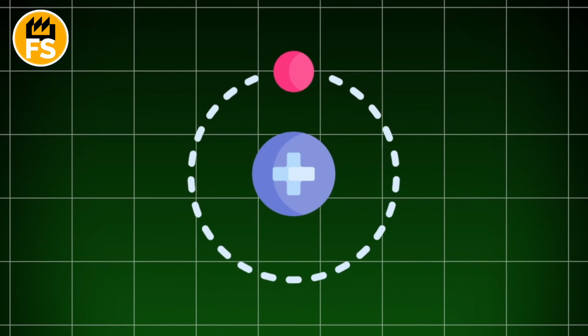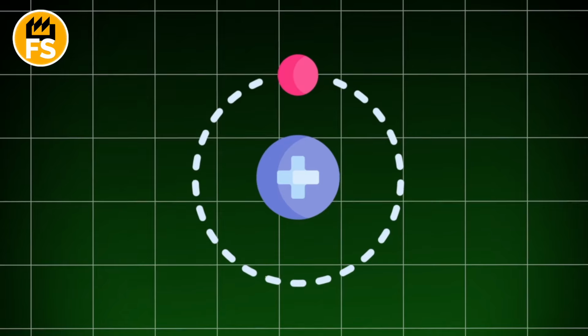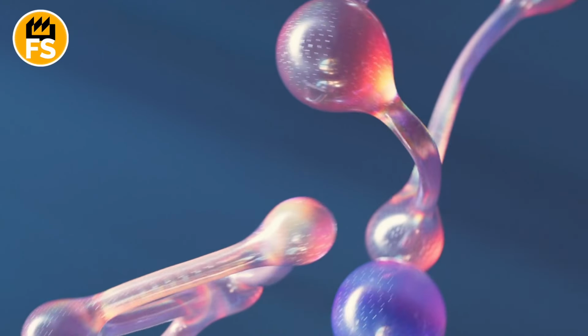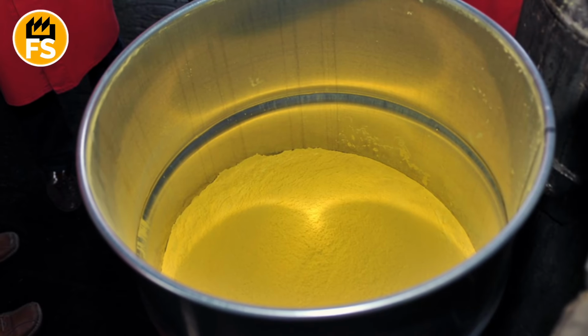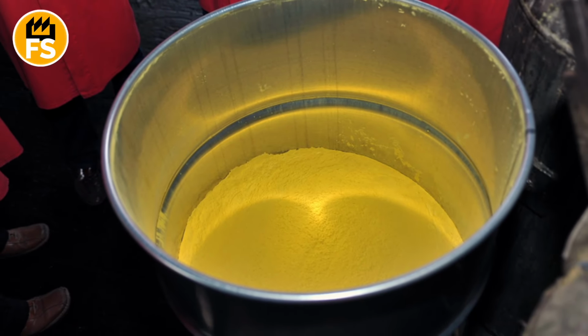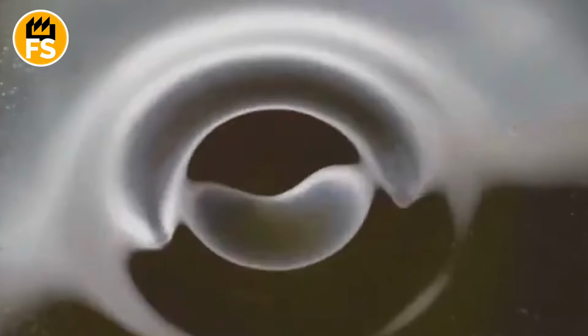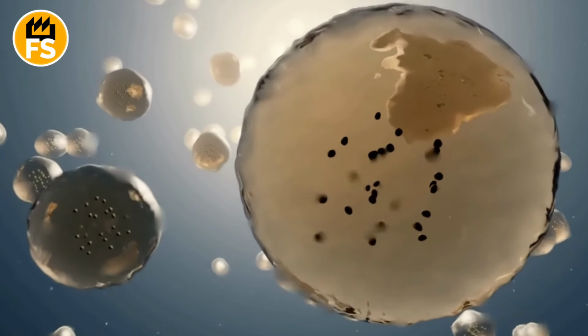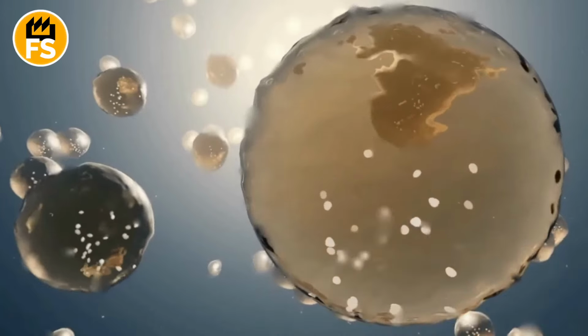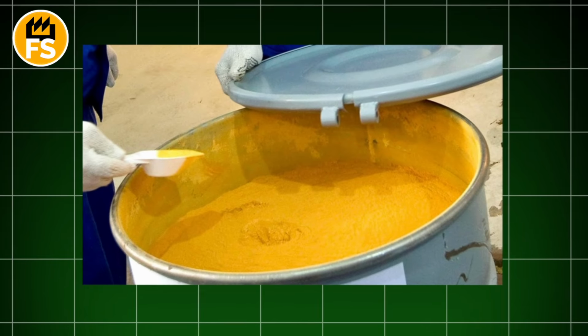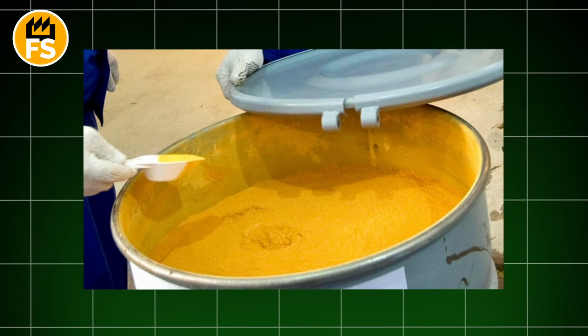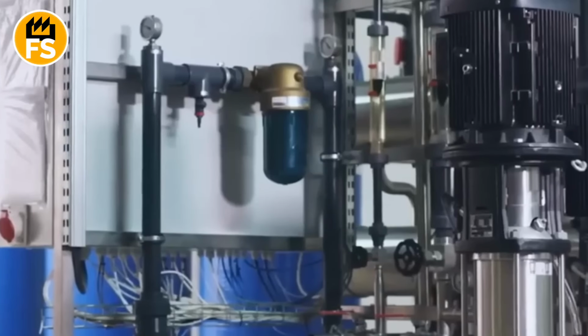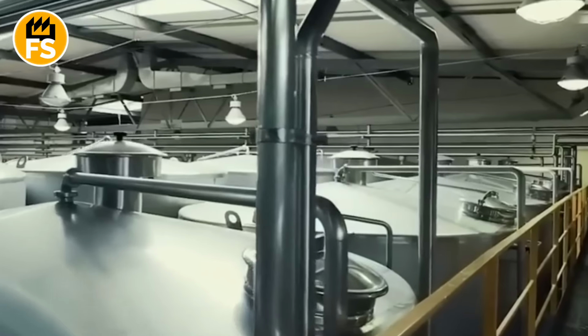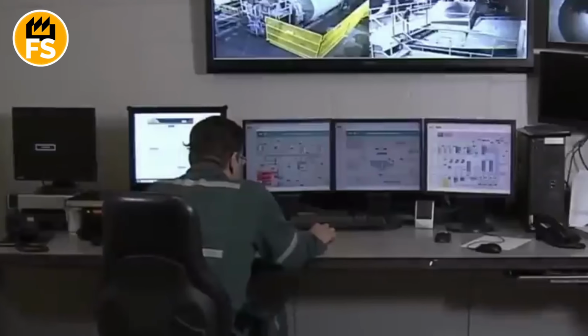Then these resins are washed with another solution, which washes the concentrated uranium off them. And so, finally, our final product is precipitated from this clean, saturated liquid. By adding ammonia or hydrogen peroxide, the uranium is forced to fall out of the solution in the form of a bright yellow, thick precipitate. This precipitate is filtered, dried in furnaces, and at the output, we get the same famous yellow cake, a heavy, radioactive, mustard-like powder. This is the uranium oxide concentrate, the first step on the long path to clean energy.